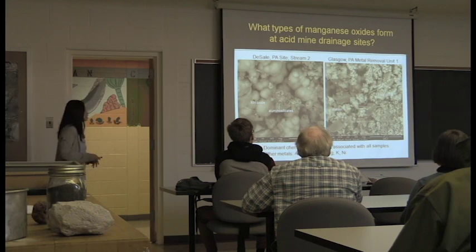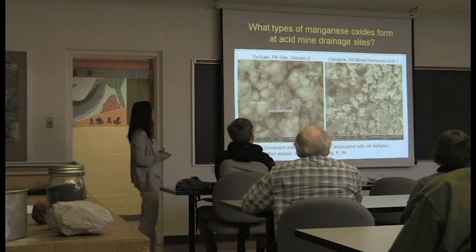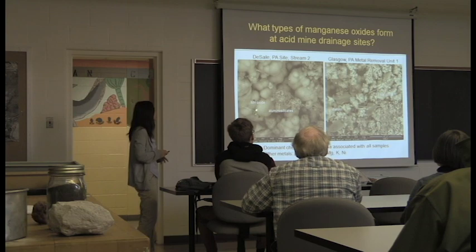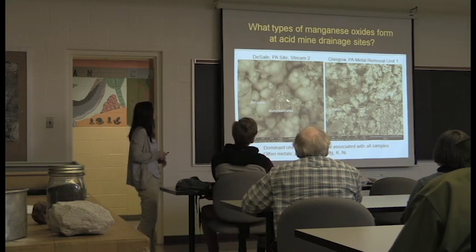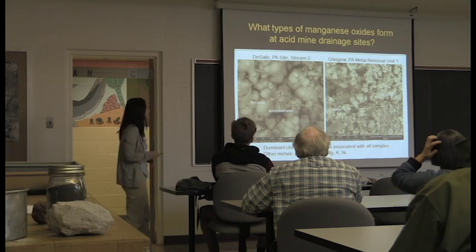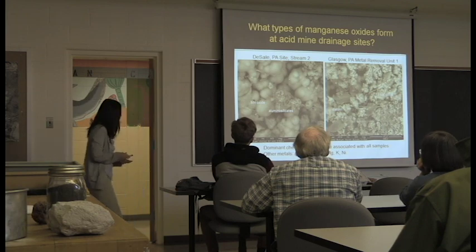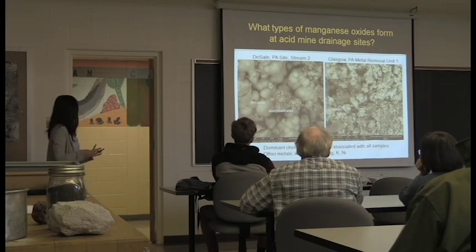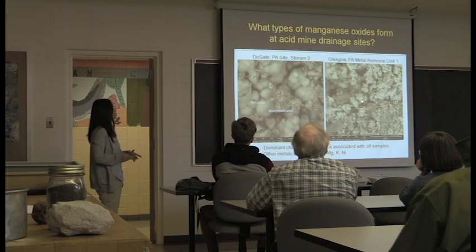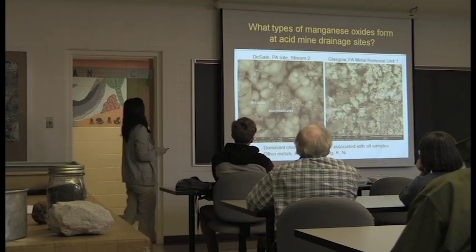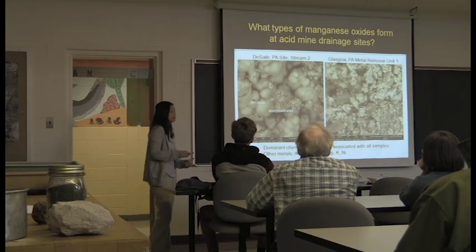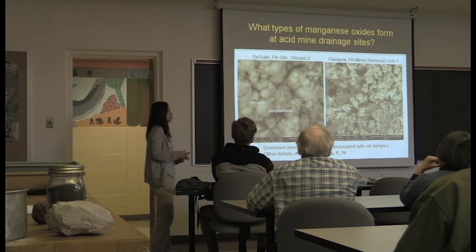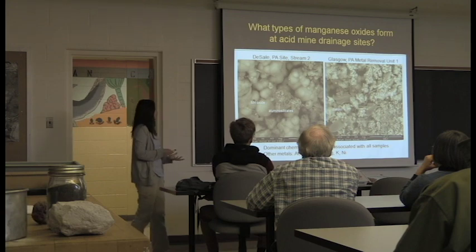You can see more of these fluffy conglomerations in a lot of our other sites. This one isn't as fluffy looking, and you also find some clays in there, some aluminosilicates mixed in with the manganese oxides. And in these you even find some diatoms, which is basically microalgae, I guess. And they're these really beautiful structures. And one question that's out there is, are these diatoms, like bacteria and fungi, also participating in the precipitation of these manganese oxides? And we don't really know that yet.